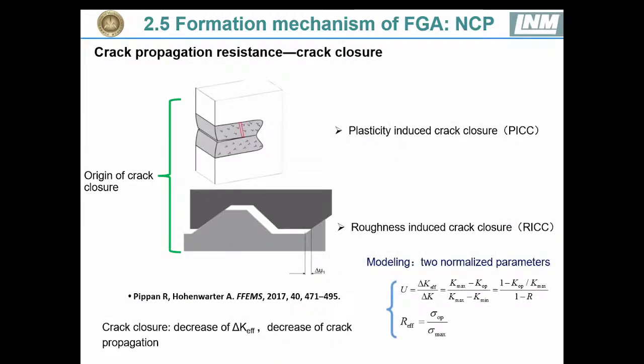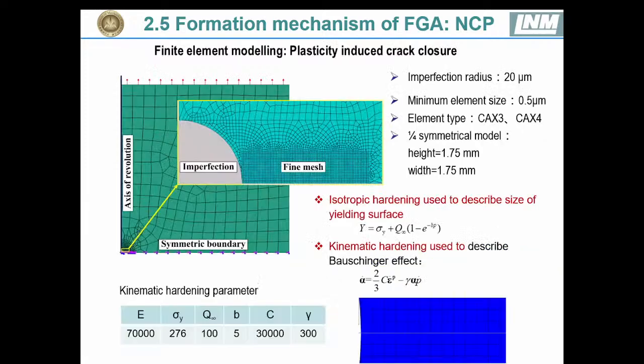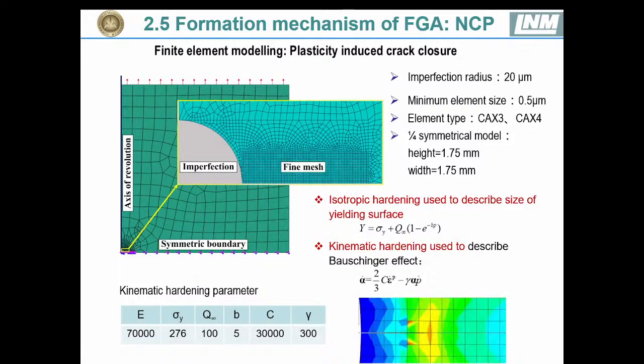And in order to validate the contact stress, here we also use our model to study the contact stress between these two crack surfaces during high cycle fatigue. Here we assume plasticity induced crack closure, and we assume that a nonlinear hardening material will be used to model this Bauschinger effect, and also for building the nonlinear effect of the constitutive modeling here.